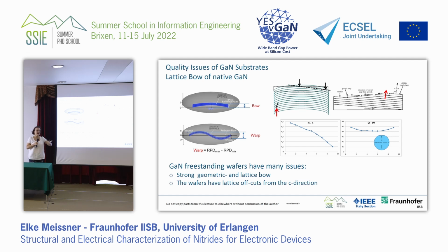So people doing epitaxy say, hey, tell me what properties your wafer has. But we know that, first of all, we have to watch properties of the crystal, because what is frozen in the crystal growth pops up with the wafer. So they can be bowed, they can be warped, they can have some odd shape. If it's not everything centrosymmetric, there can be crazy shapes of wafers, especially for the nitrides where the technology is not really utmost mature. So if you consider gallium nitride freestanding wafers, you see that there are many issues to these wafers, which is strong geometric bow or lattice bow, and you can have offcuts from the C direction.